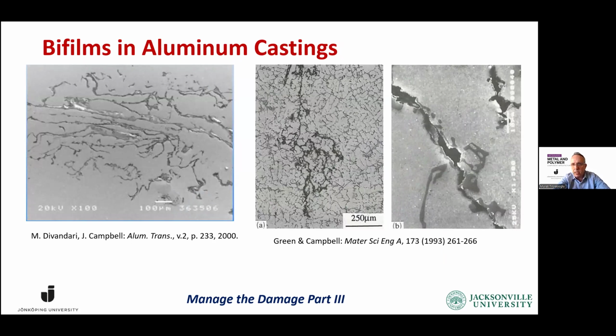And as you can see, several examples from the literature. It can be a huge bifilm like this, and you can see one half of the film on this shiny surface, and the other half was removed during grinding and polishing. Here's an extensive bifilm, and if you zoom in, you can see that this is an unbonded surface. It's basically a crack that is in our casting.